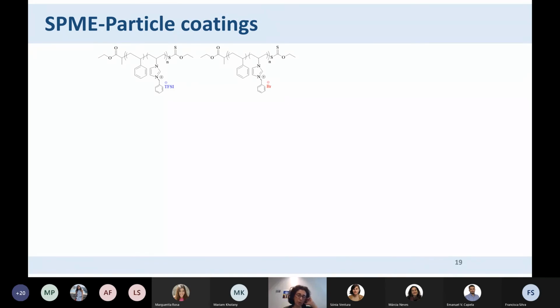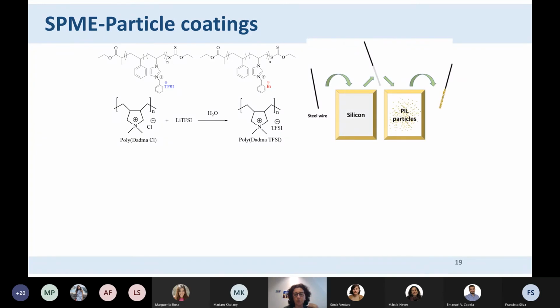The most interesting thing is that we started to realize that the thin coating would also not work very well, because I have very small volume, and so I expose the fiber for a very limited period of time, and the fiber is already saturated. These samples that we have been using were all at the same concentration, but if I have a very small concentration, I would never be able to detect the compounds in very small concentration.